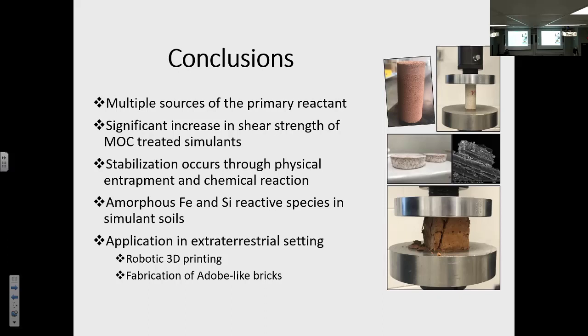So applications in terms of extraterrestrial setting can be both. Yes, the robotic arm and 3D printing seems really, really cool. But honestly, if it were up to me, I would just make molds and create bricks. And that's exactly what I did. I used a silica mold to create these bricks with the magnesium oxychloride cement. And the mortar is our own proprietary mix. So there's plenty of options, but I think the idea is to have an open mind, and sometimes looking back is the best way to start something new.